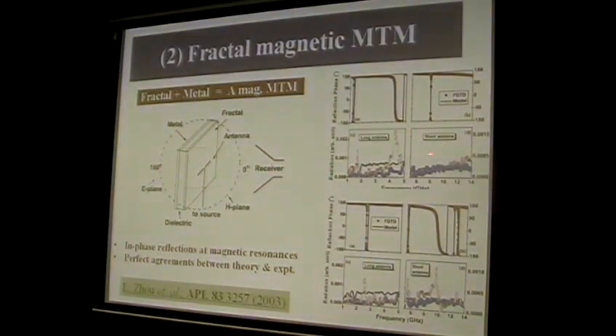So indeed, you can find that at this particular frequency where the magnetic response is predicted, we do find that the radiation is strongly enhanced at the peak. That directly demonstrates that indeed at this frequency, a magnetic response is here. So this is the direct experimental demonstration that indeed this system is a very good magnetic material.